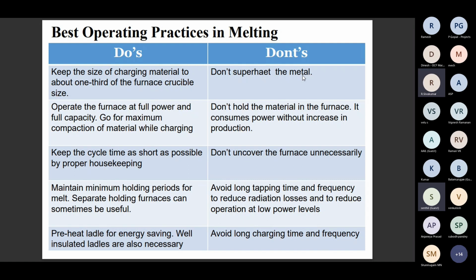Best operating practices in melting, do's and don'ts. So far we have discussed around 10 to 11 best operating practices, and the do's and don'ts are very important. Keep the size of the charging material to be 1/3 of the furnace crucible size, do not superheat the material, and operate the furnace at full power and full capacity. Go for maximum compaction of material while charging, and keep the cycle time as short as possible by proper housekeeping.